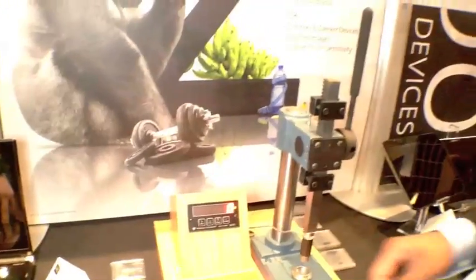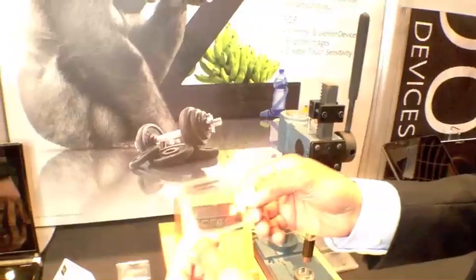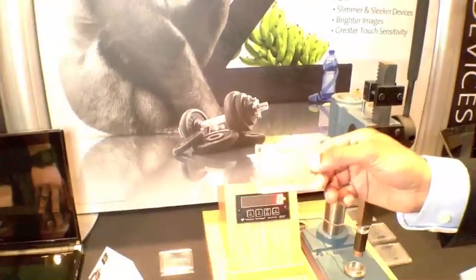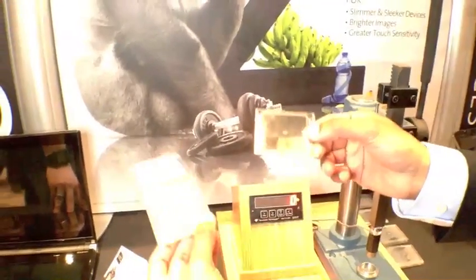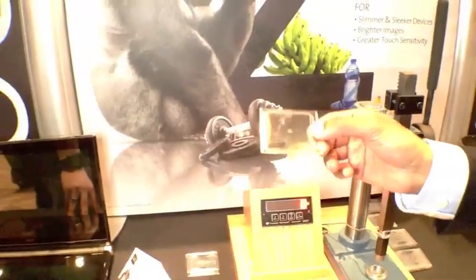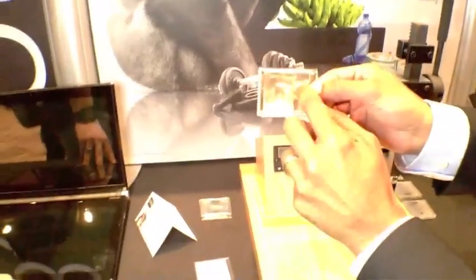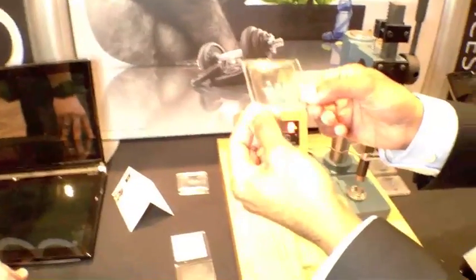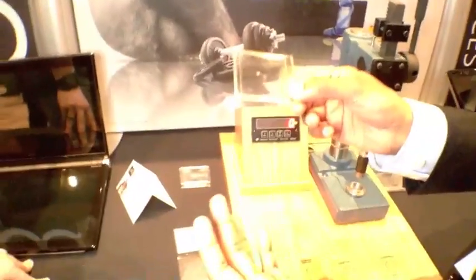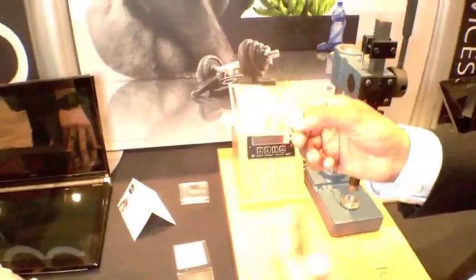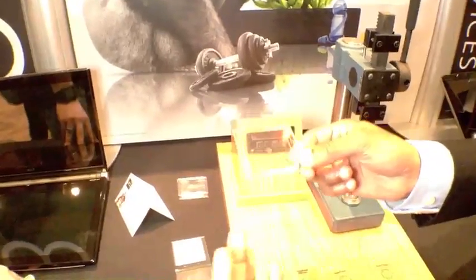This is a lever press. What we've done with the glass is we've abraded the glass with silicon carbide particles. By abrading the glass, we introduce damage to the glass. We try and mimic the kind of damage that a phone would see inside a person's pocket or in a purse.